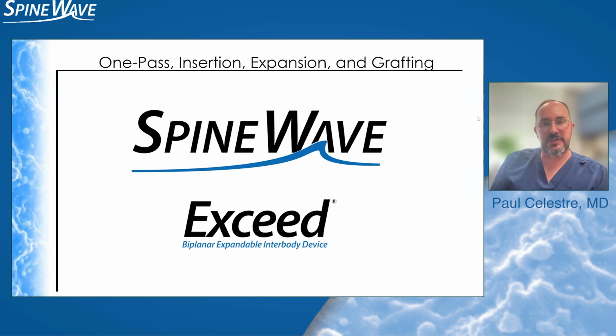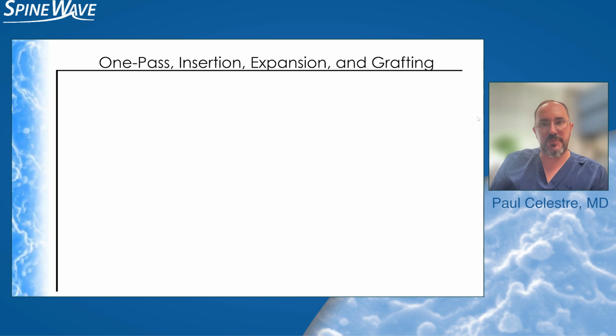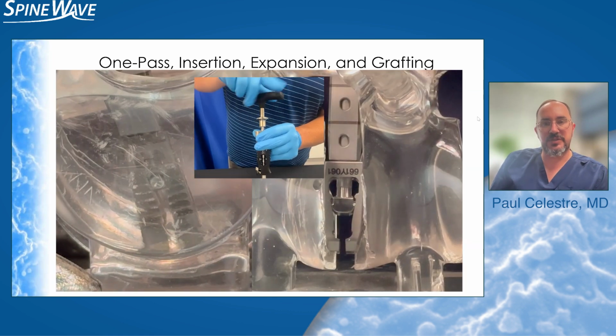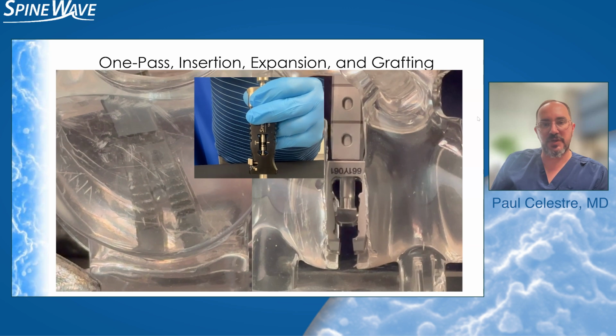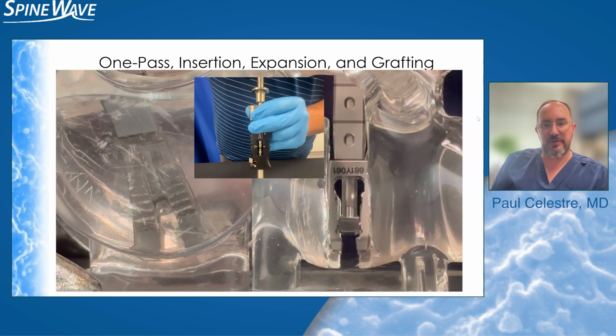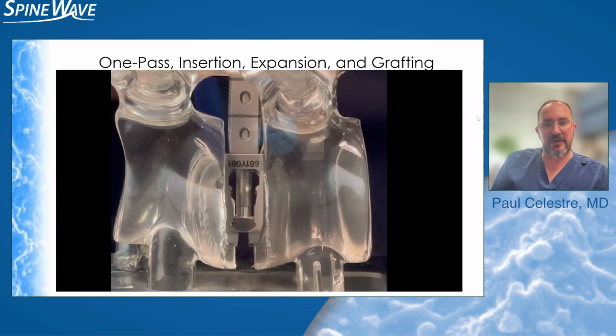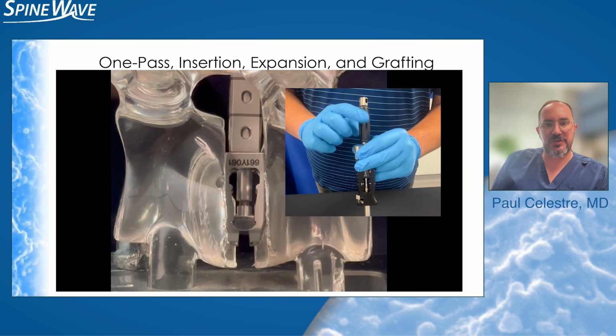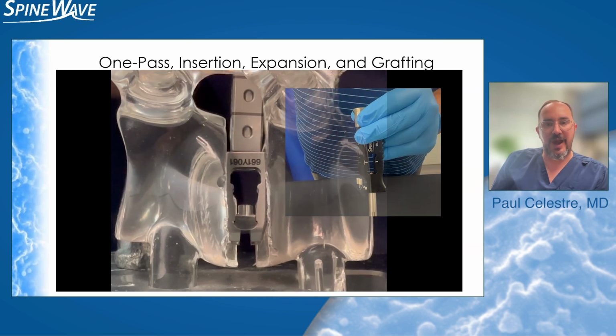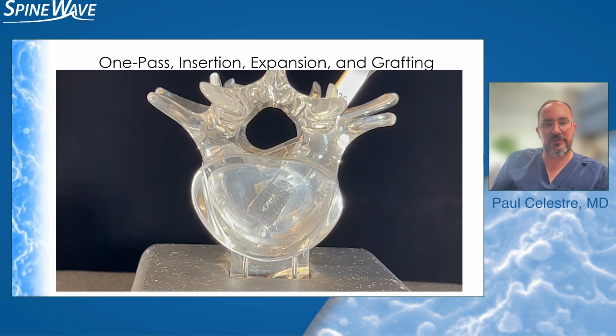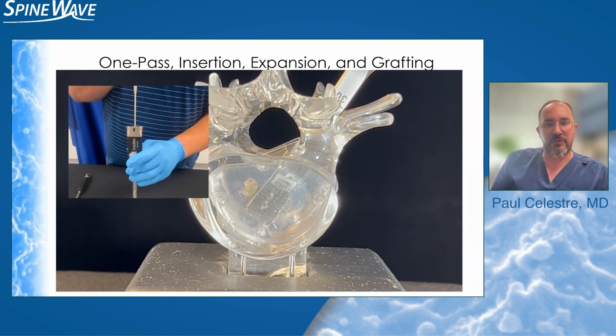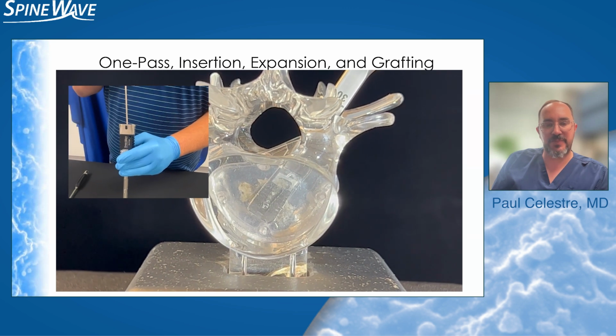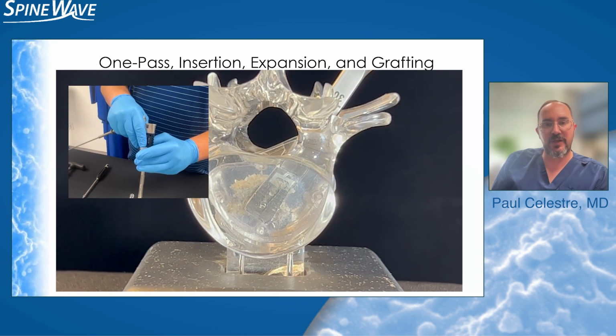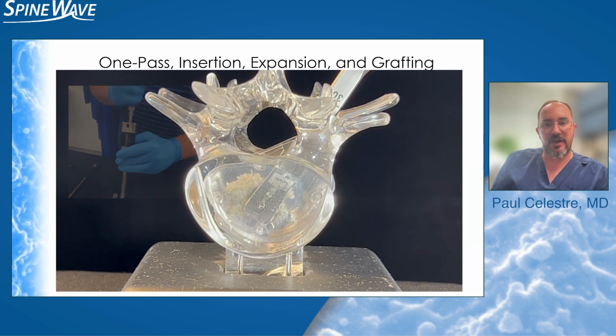In this brief video, you will see how the cage can be not only expanded, but also backfilled with graft. Here you can see using the T handle to drive that wedge forwards, fully expanding the cage in a biplanar fashion. You will both feel and hear a click when the cage is completely expanded. Then the rod that drives the cage expansion is removed, and you can insert the graft packing device directly through the cage insertion tool. This is a very robust interface and allows you to aggressively backfill the cage as well as the disc space without any risk of bone graft extruding from between the inserter and cage interface.